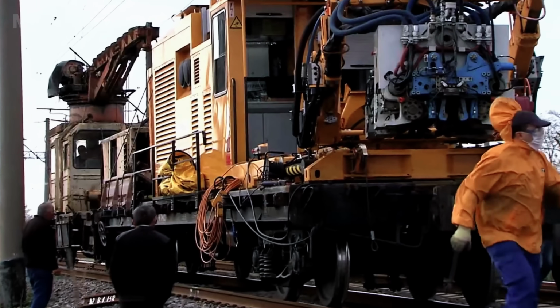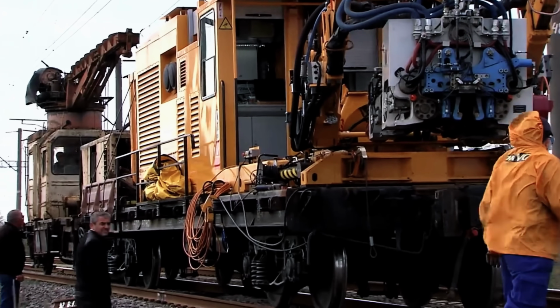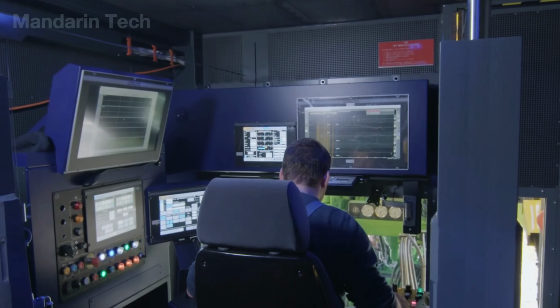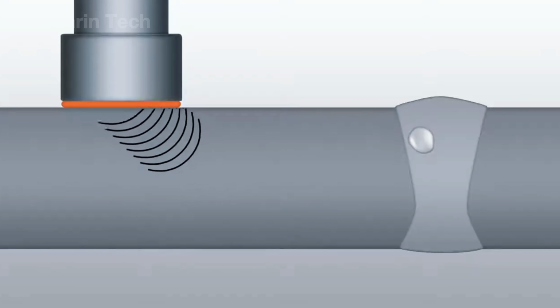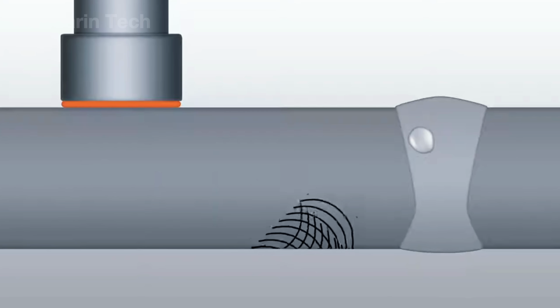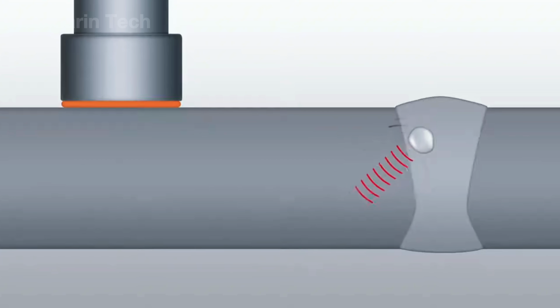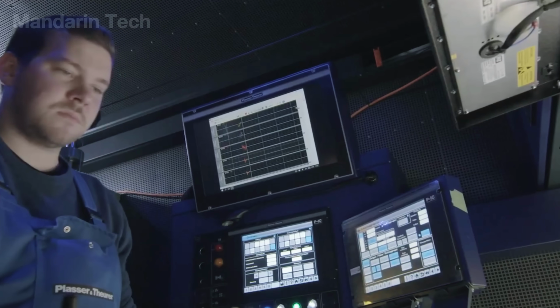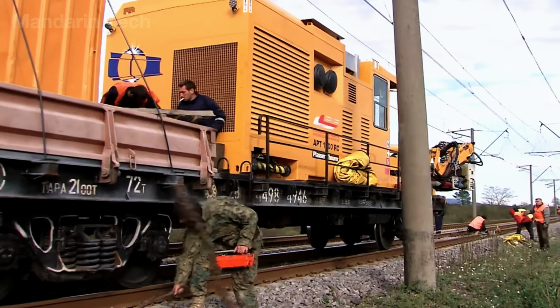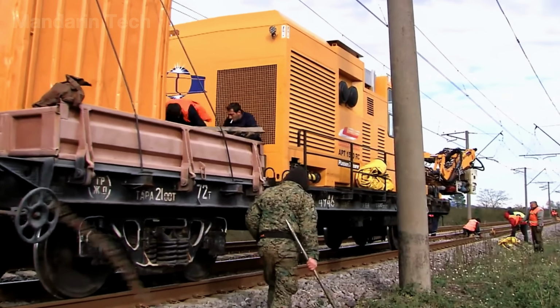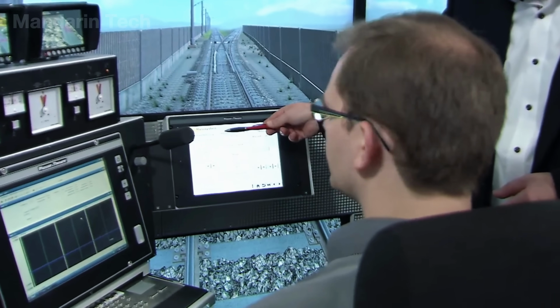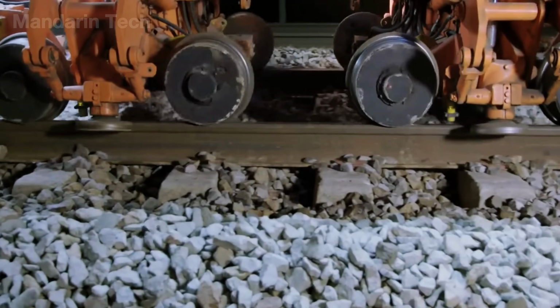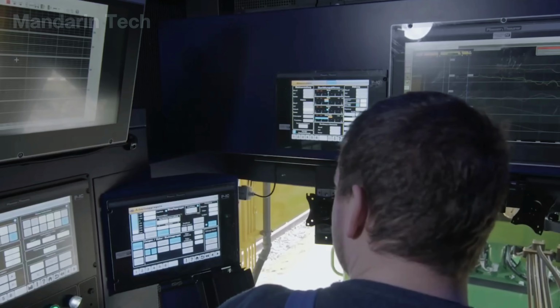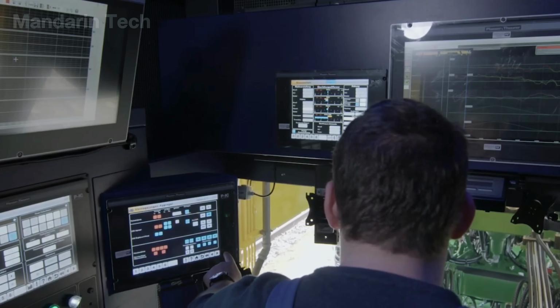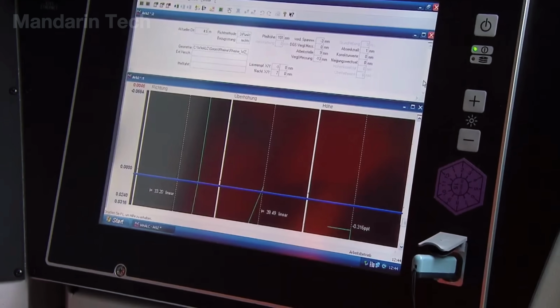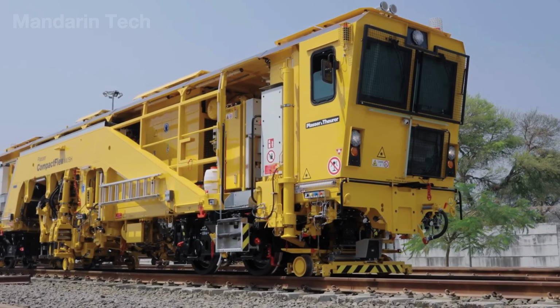Once the entire rail line has been welded and ground smooth, the final inspection begins. Engineers use an ultrasonic flaw detector to scan the rails, detecting microscopic cracks or internal voids hidden deep within the steel, flaws invisible to the naked eye. A track geometry car then measures elevation, tilt, curvature, and gauge width with precision down to 0.02 inch. Any deviation beyond tolerance is corrected immediately using tamping and alignment machines.